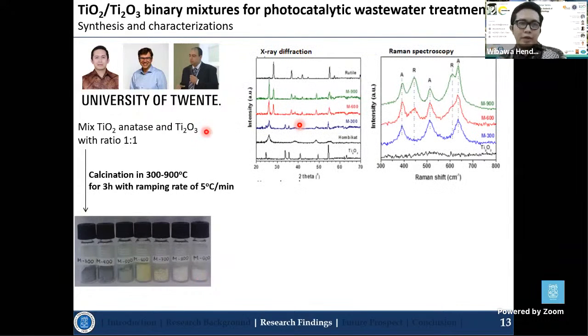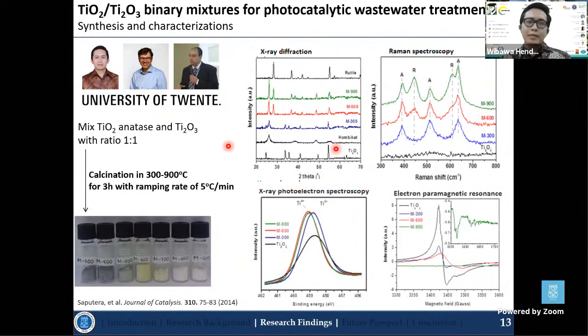So based on the X-ray diffractions, it can be seen that the anatase and rutile phase is actually generated by calcining at 600 degrees C and 900 degrees C. However, at 300 degrees C is only anatase phase. And based on the Raman spectroscopy, XPS, and EPR, it confirmed that the titanium 3+ defects is successfully generated in titanium dioxide.